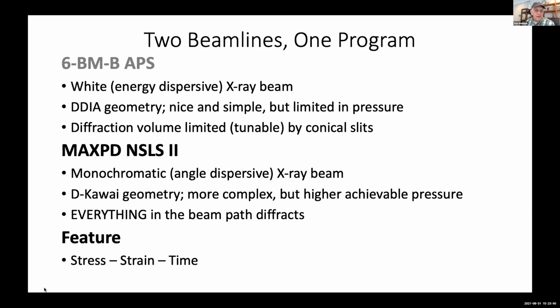The one at APS is a D-DIA, going back to the early days when we brought that into existence. And the one at the NSLS2 is, for us, a newer system, but it's based on the Kawai geometry of 6/8 anvils, with the 111 axis vertical, and the top and the bottom rams move in on the sample to generate differential stress, as the 6 other rams are maintaining the hydrostatic pressure.